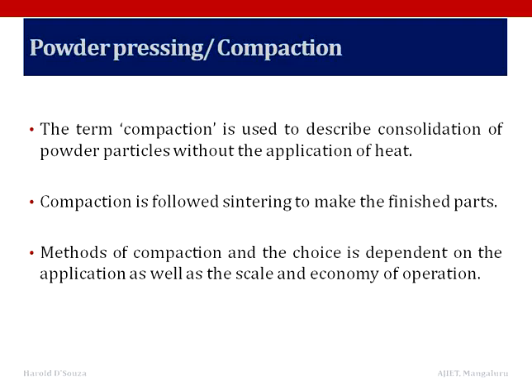In many cases, it may be advantageous to cold press a mixture of the component powders because of ease of compaction. However, it may not always be advantageous. Let's consider, for example, sintering of compacts containing elemental zinc is difficult, while pre-alloyed brass powder is easily cold pressed and sintered. Now, generally, pre-alloyed powders are hard and cannot be readily cold pressed.